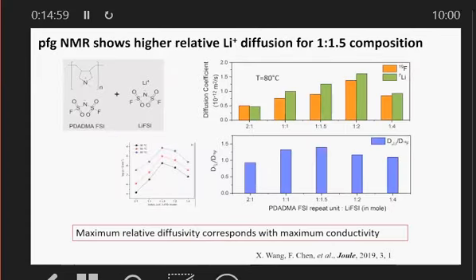We're also very lucky to have at Deakin a strong NMR team, which I established about 15 years ago now with Luke Odell, and we have a pulse field gradient diffusion measurement device, which allows us to do multi-nuclear diffusion measurements. So here we have lithium for the system I was just showing you. On the top here we have the diffusion coefficients at 80 degrees Celsius, a high temperature, of the lithium and the FSI anion. And we see that as the composition increases with lithium FSI, the diffusivity goes up initially and comes down again.